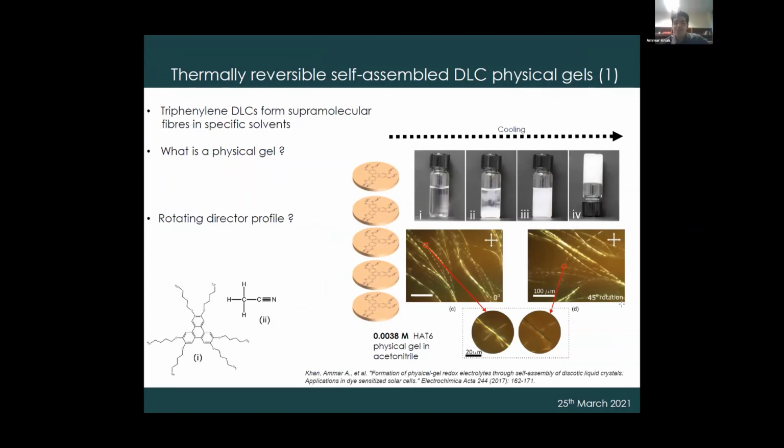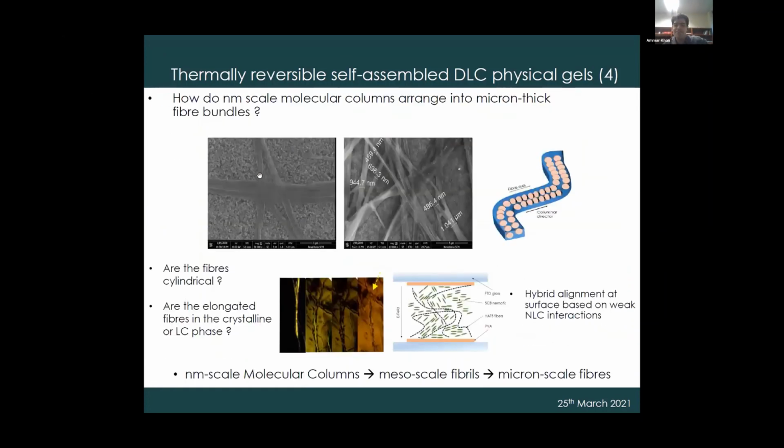That's what I also thought initially. I thought that this is a very regular pattern, and I spent quite a lot of time looking at them a lot more carefully. It turns out they're not that regular. They look regular in this case, but in the same sample you can have different regions exhibiting different length scales. Even here, you can see that they're closer in some fibers and further away in others. I thought this is because of some unintentional chirality in the system or something else. But the best explanation that I could give is that we have these fibrils forming large bundles, and these bundles are twisting every now and then, and it's the twist of those bundles that's giving us this scattering.